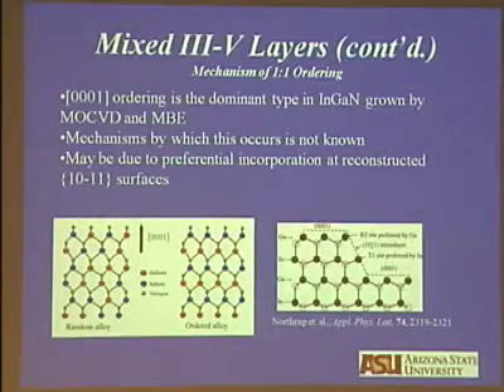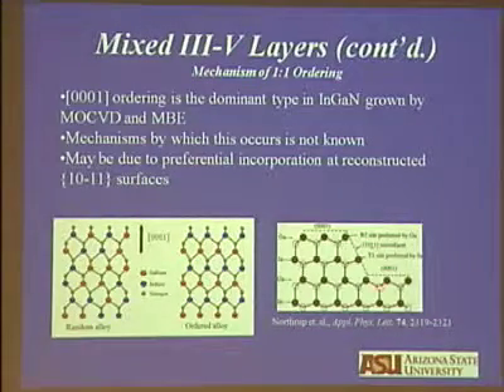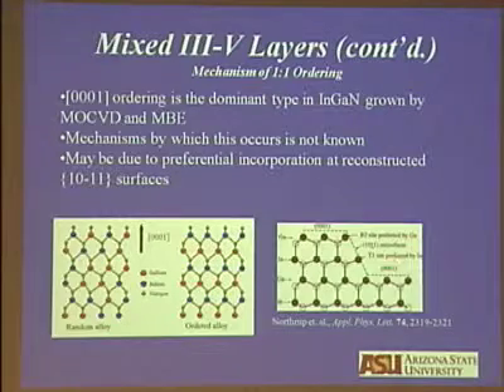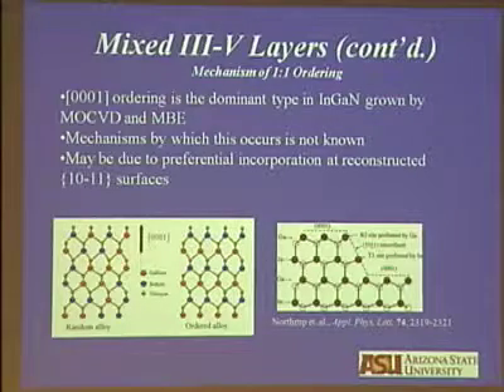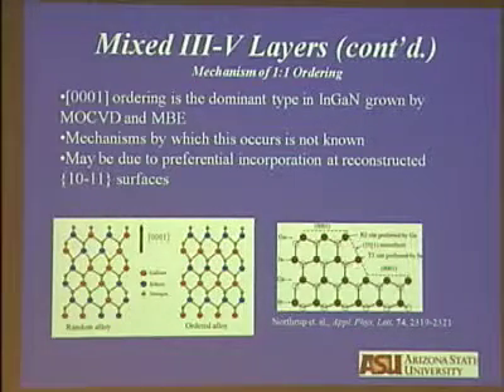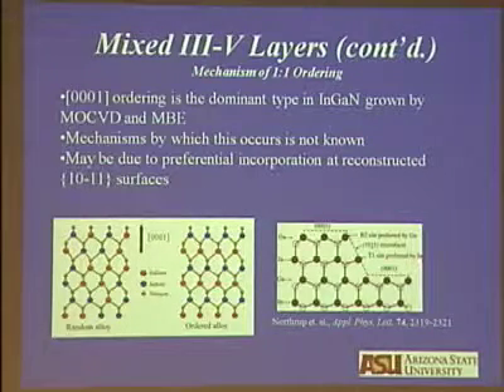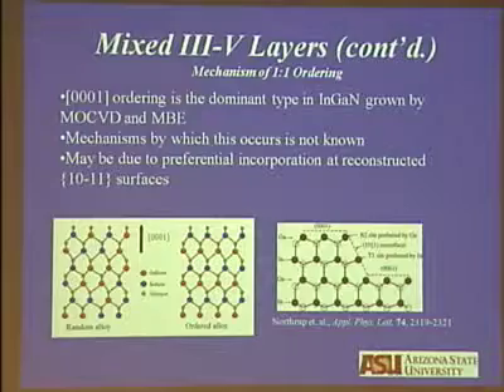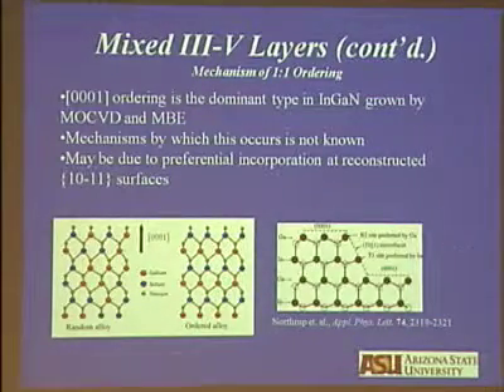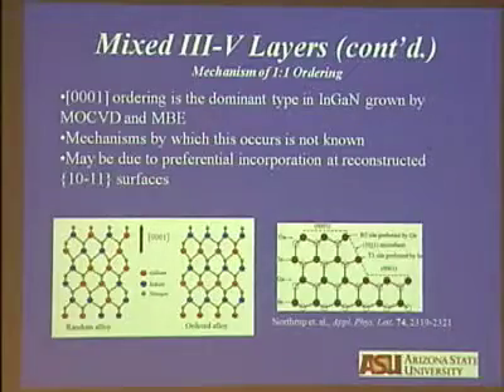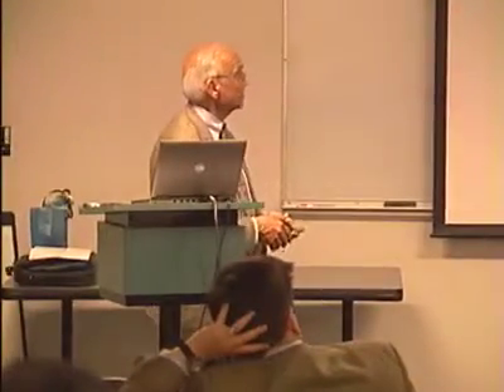And why does it do that? According to Northrop, if you look at the 1-0 bar 1-1 facets, as shown here, they are the preferred site for the attachment of gallium atoms, and the T1 site is the preferred site for the attachment of indium atoms. There are reasons for it. You can see that it can continue. And is there evidence? Some evidence we have, but it is not clear cut that indeed that happens. And that's the issue: phase separation and atomic ordering do occur, but we don't fully understand the mechanism by which ordering occurs in these materials.